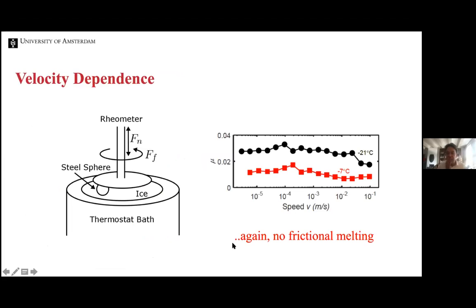The first experiment we did to try and see what happens is we measured as a function of the speed of the sphere sliding over the surface. And we basically find over more than 4 orders of magnitude that the friction coefficient is very low. It's here something like 0.01, very, very slippery, but doesn't really depend on speed. Yeah, and this is again an argument against frictional melting, because if you go very fast, you would expect a large amount of frictional melting, and if you go very slow, no frictional melting. And so if the frictional melting is important, you would expect the friction coefficient to depend on speed, which it doesn't.